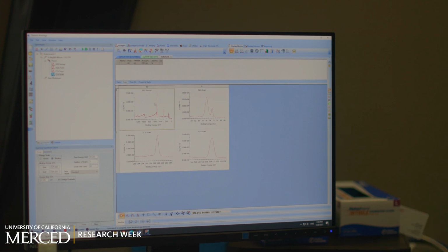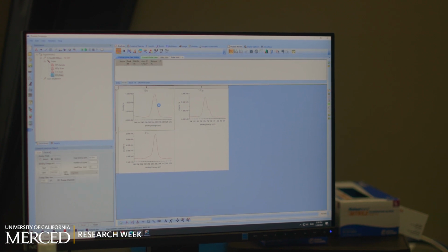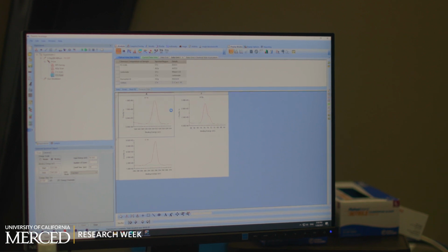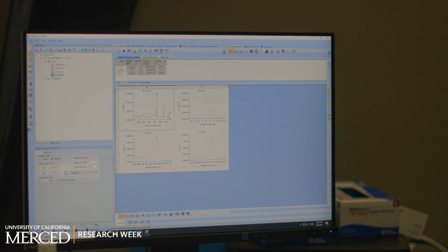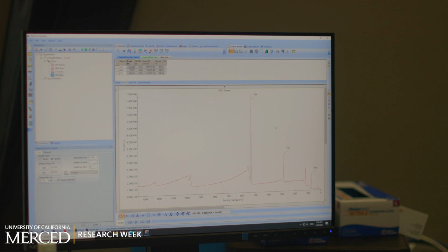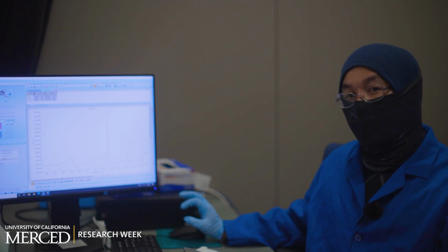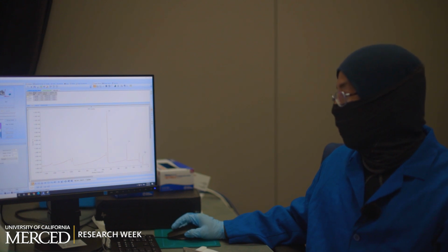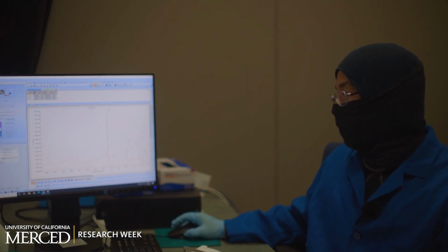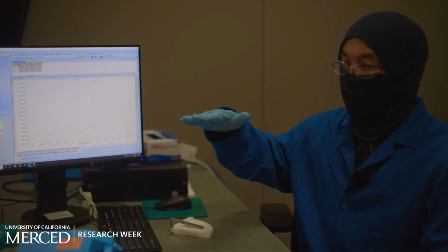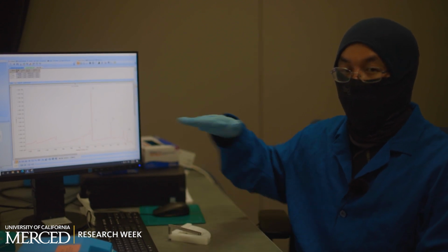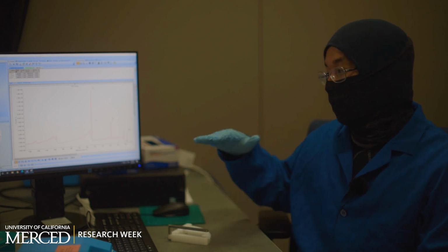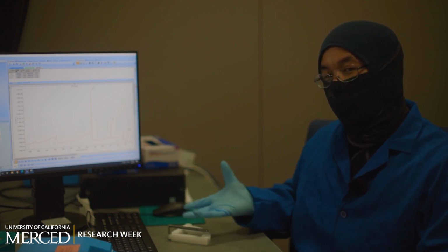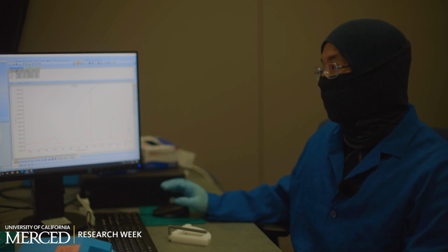But if, say, you didn't know what the sample was, you could also do an XPS survey, analyze the whole spectrum, and then do an auto ID and have the software analyze your sample for you. You can see here the software automatically identified the peaks for aluminum, oxygen, and carbon. So for XPS, this is really good for analyzing the surface of your material and determining what kind of materials are present on the surface. When you characterize different materials, the bulk or what's inside the sample may be different from the surface. Especially when you're looking at nanoparticles, the surface properties may be a lot different from the bulk properties for the whole material. So XPS is pretty useful for analyzing the surface properties.